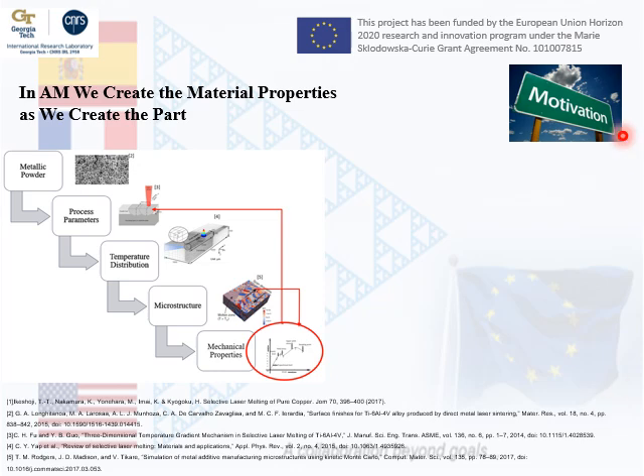Excellent. So in metal additive manufacturing, we utilize metallic powders and a heat source to melt local volumes of powder that upon solidification allow building a component layer by layer. This technique is very well known for plastics, but recently it has also been utilized for metallic parts. Additive manufacture has become a very relevant industrial process, and we expect that in the future this process is going to be even more relevant. After solidification, the microstructure has been found to diverge from the microstructure found after conventional processing. The reason for this is the solidification, and also the application of the laser.